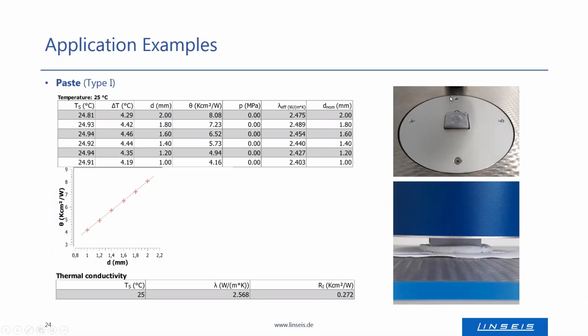The paste was directly applied onto the meter bar, and during the decreasing sample thickness, the excess material was squeezed out. In this case, it was not removed, but it is also possible to remove the excess material.